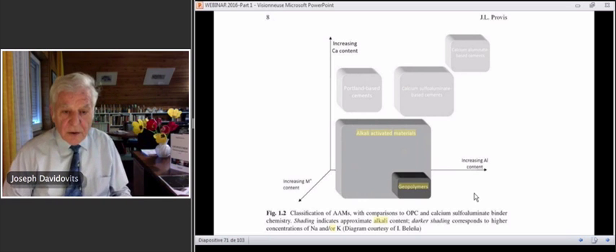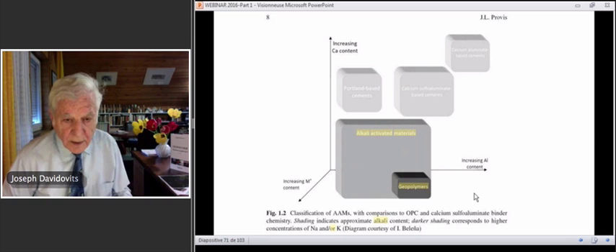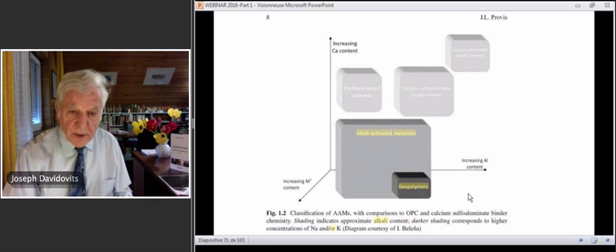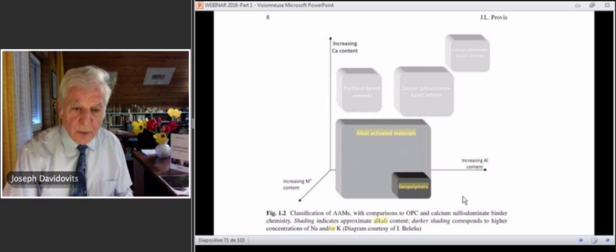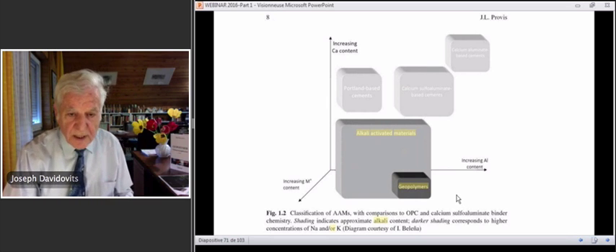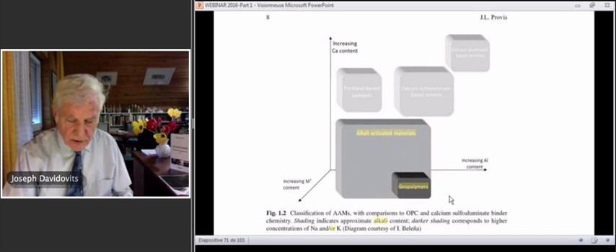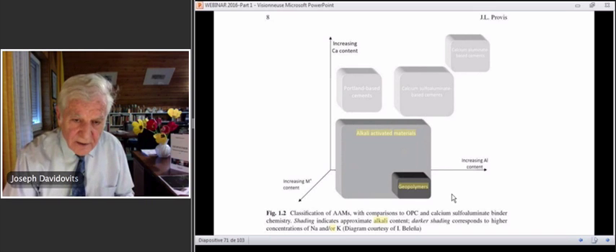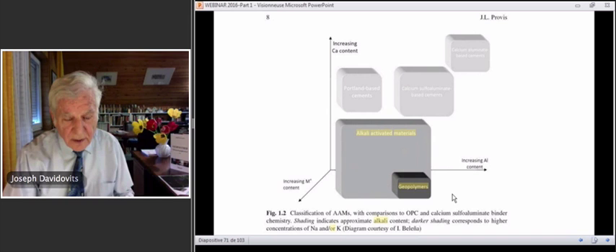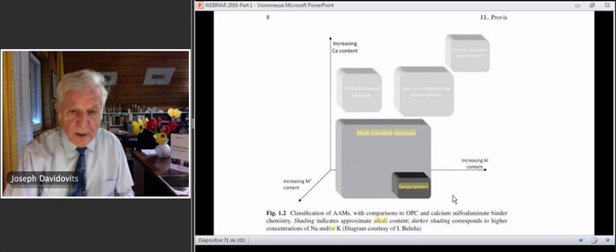Well, my friends, I also made alkali activated material. I have been asked by companies to develop for them alkali activated Portland cement. It is an alkali activated material. You make a cement, 50% Portland, you add 47 or 48% fly ash, and then some alkali activator, like sodium sulfate, for example, and you have a material that hardens, that is a cement. This is alkali activated material. It is not geopolymer. It has nothing to do with the geopolymer, with the polymeric structure. You cannot compare this to geopolymer and take it as a subset of alkali activated material.